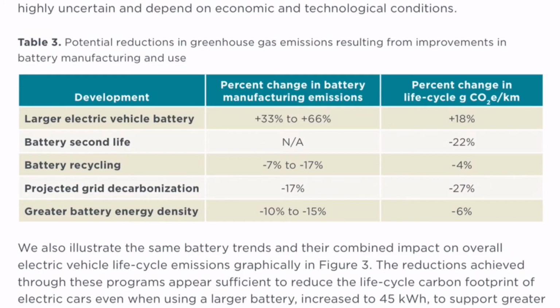And this graph really wraps up nicely on the manufacturing side the effects of different parameters, the most important being battery size in kilowatt hours. That can increase overall manufacturing emissions by a third to two-thirds, which can account on a per kilometer basis for an 18% premium in carbon emissions. Now, second life and battery recycling can also significantly cut back and almost completely offset the larger size of a big battery. But the most important reduction, accounting for 27% in life cycle reduction in CO2, would be grid decarbonization.